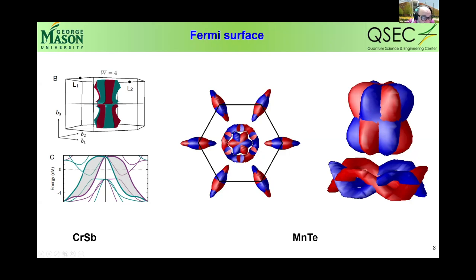The other thing is, this band structure is, unfortunately, I had to cut the bottom, that was a long path, but it's basically going to two different points. One starts from the gamma point, and the gamma point, of course, is always degenerate. Then you go along two different directions of the hexagonal unit cell, different but not opposite. If they were opposite, then the spin splitting would be the same. This manganese telluride, as opposed to chromium antimonide, is formally a semiconductor, although in experiment it always comes self-doped. And here, for illustrative purposes, I combined Fermi surfaces with small hole doping and small electron doping.